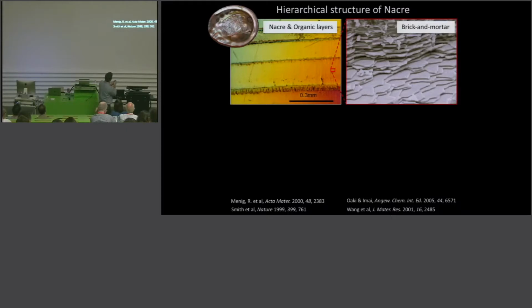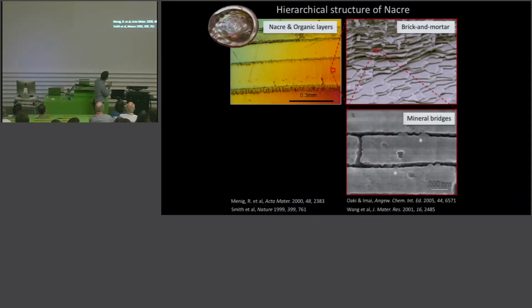Now, if we zoom in on the nacre layer itself, and you're probably familiar with this, you find this beautiful brick and mortar structure. So these are platelets of calcium carbonate, more specifically aragonite, which are organized in this beautiful way in a brick and mortar architecture. Now, if we zoom in at the interface between these platelets, you'll find something really interesting. You'll find that some of the platelets are connected through what we call mineral bridges. And this has to do with the way the organism builds the material. And some of these are really connections from one platelet to the other, and some are just asperities.